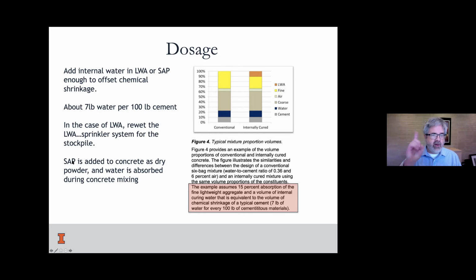In the case of SAP, however, we really don't want to bring that water in with the already saturated SAP. This would be a globby mess, to be quite frank. So what we want to do is add it as a powder right when we're working with a mixing operation. So we can add it in, we've added it into the back of the truck. It actually goes in pretty well. Our testing shows it's quite homogeneously dispersed. So, you know, always wondered about that.